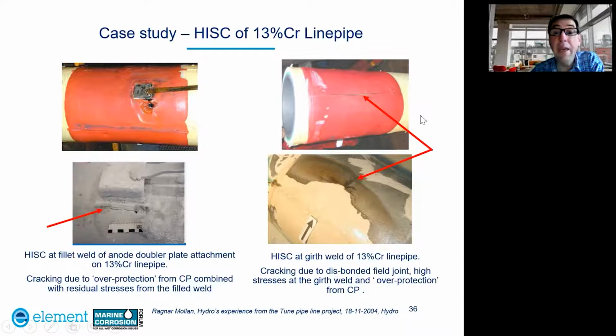So the other example here, you can see that a crack appeared in the field joint coating on the line pipe. When this was investigated, you can see here the crack was actually in the 13 chrome pipe and spanned this girth weld. So the cracking in this example was due to the disbonded field joint, the high stresses at the girth weld, and the overprotection from the CP system, generating an excessive amount of hydrogen.